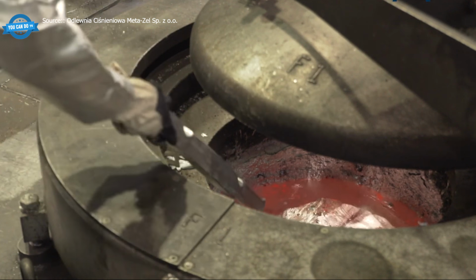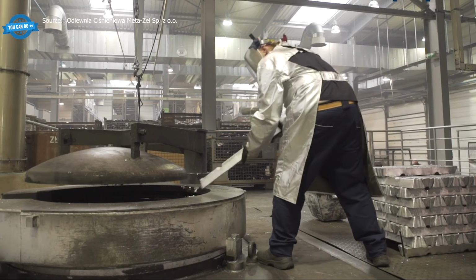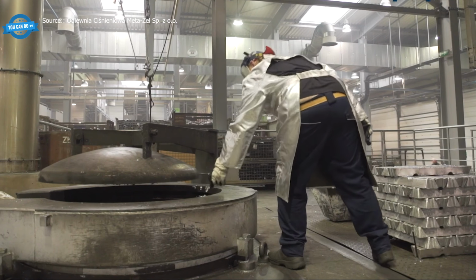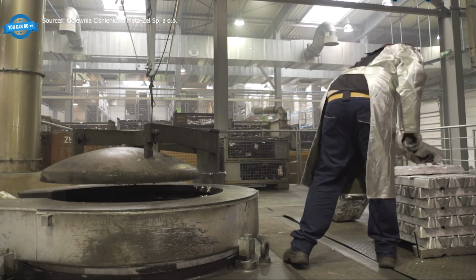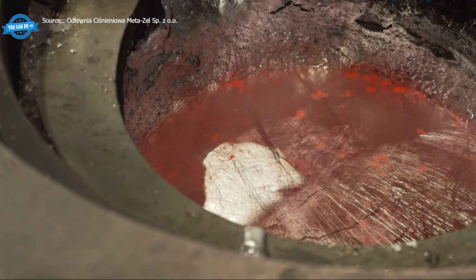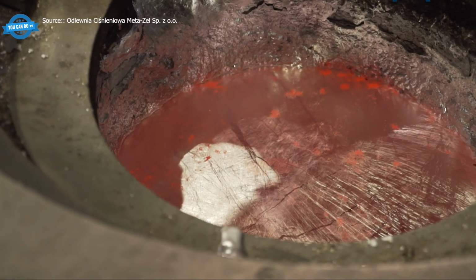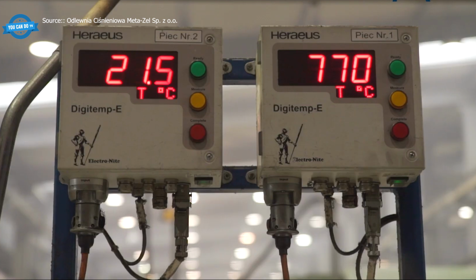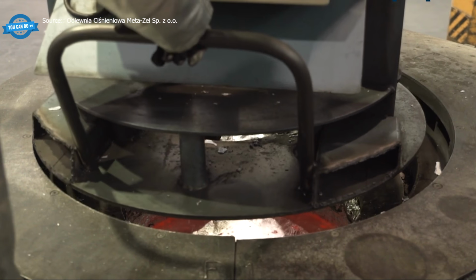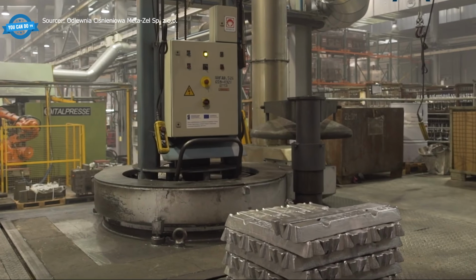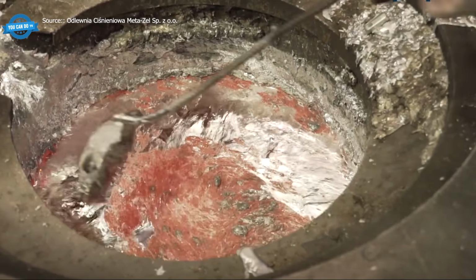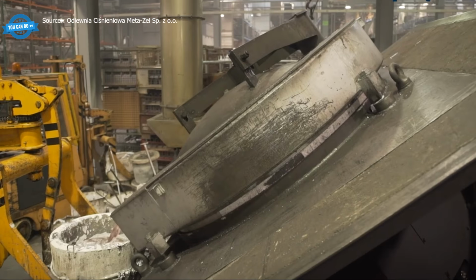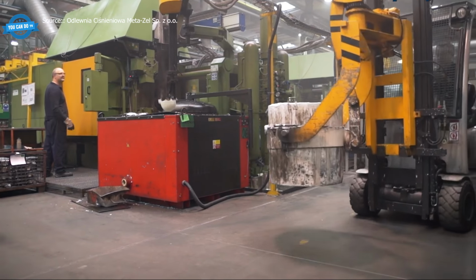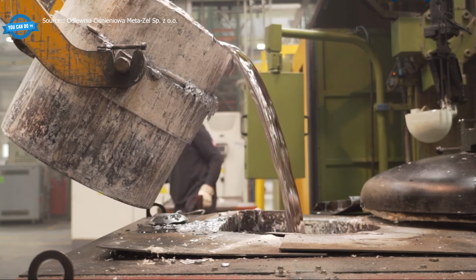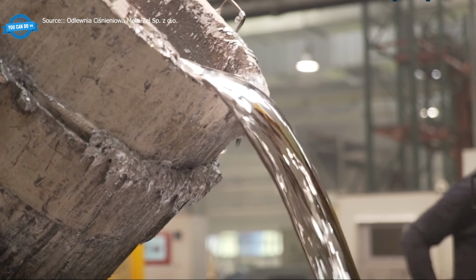Once the die casting machine is running, everything upstream has to keep up. The aluminum arrives as ingots and gets melted in induction furnaces at rates around 1.5 tons every 45 minutes. Molten metal is refined with argon, rotated through the bath to strip out dissolved gases and floating contamination. The purified aluminum is transferred to holding stations that keep it liquid until the machine is ready.